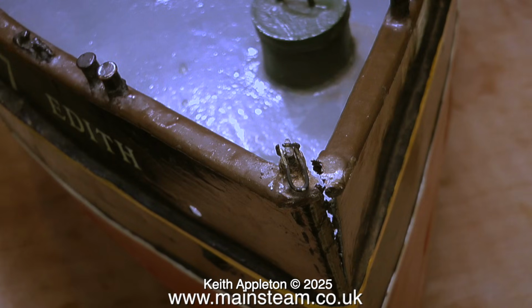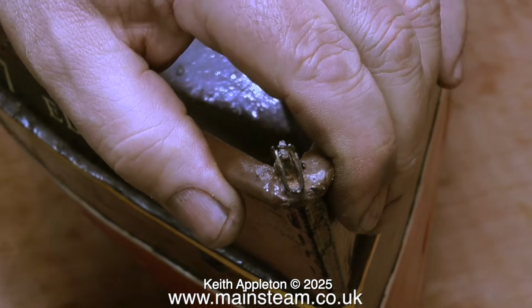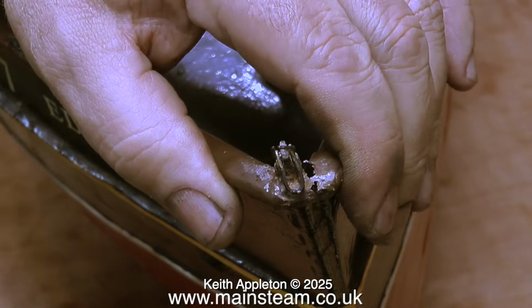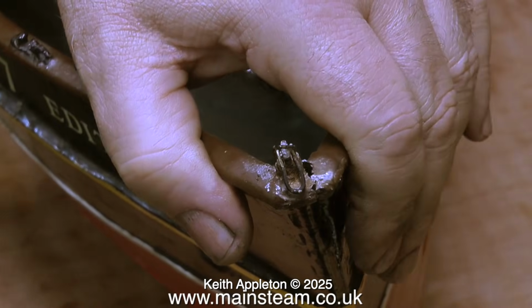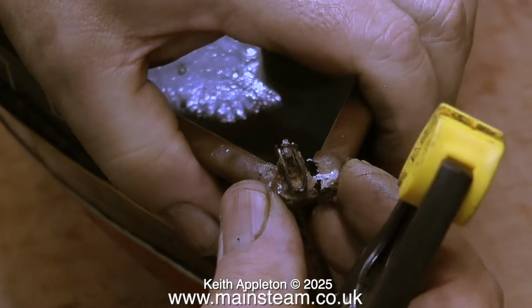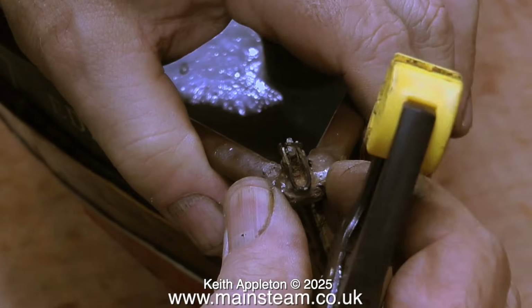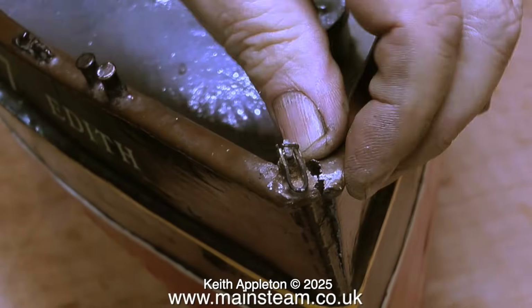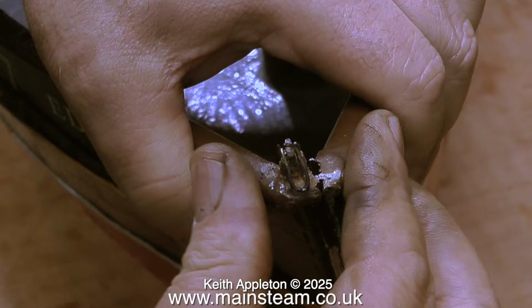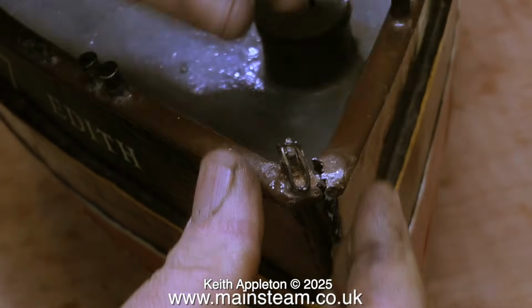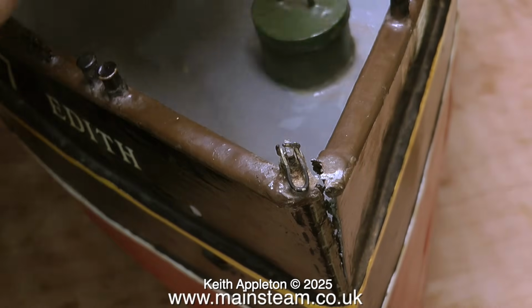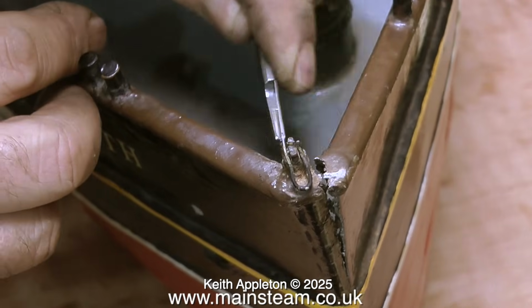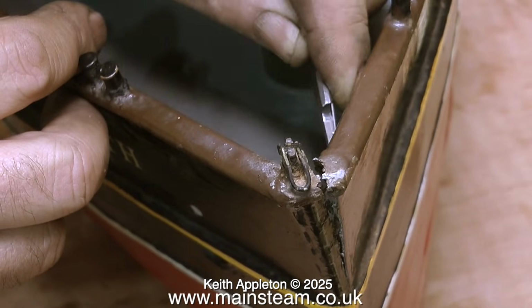The bow of this boat is quite badly damaged, as you can see. It's come loose and sprung apart. Originally this part of the bow was soldered together, but it's just given way over the years, and this is a bit of a problem because I can't resolder it for a couple of reasons. The main one being, of course, that the paint will be removed by the heating process, and the other reason is it's not a good idea to put any heat into a thing like this because the heat will make the plates move about, and that could cause many more problems.